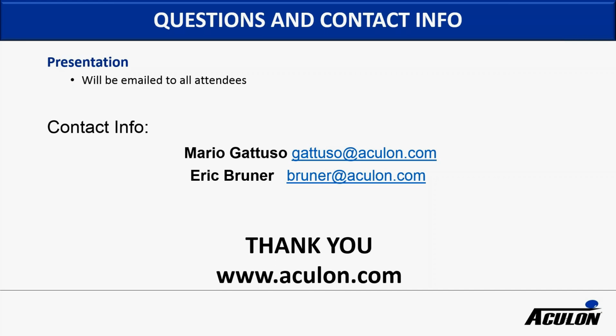Thank you, Edward. Next question is, would it be possible to apply a hydrophilic solution onto VHB or acrylic foam to increase the adhesion of a silicone gel? So I'll let... What's that again? The question is, can a hydrophilic solution be sprayed onto an acrylic foam to increase the adhesion of a silicone gel? Potentially, but we would have to test that. We've done adhesion of, like the agarose gel, for example, to PMMA, and the TMC style chemistry that we use to get adhesion of materials to siloxanes might also adhere to the silicone gel, but it comes down to chemistry.